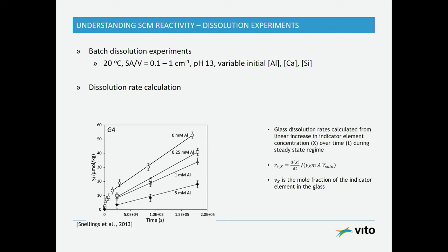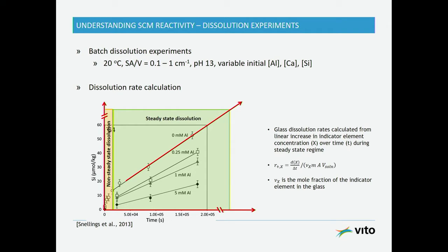So how do we calculate the dissolution rate here? Well, it's using this kind of formula. And here you have then the slopes, the buildup of, for instance, silicon in the solution here. And then you actually take the slope, and this is a measure for your dissolution rate. You want to do this over a limited time period, because at some point, when the concentrations go up, you will reach a hydrate solubility product and you will get precipitation, so you don't want to end up in there. So if you really want to see only the dissolution, you have to stay within this time period.